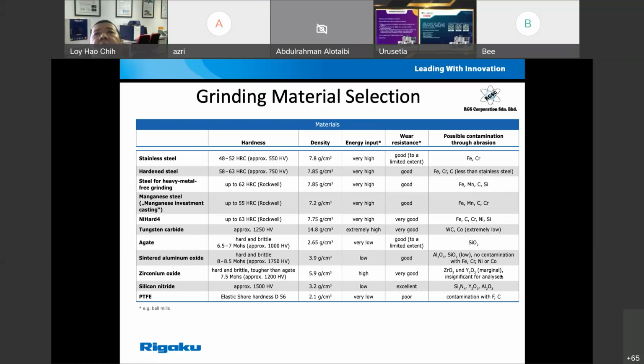For instance, if you are trying to measure iron ore samples and you want to detect the iron, and you are using a stainless steel vessel, then you're going to have a much higher Fe or chromium inside the samples. This kind of error is contributed by your sample preparation. Maybe your samples do not really have such a high Fe or high chromium, but your vessel is contributing to that. So this will give you errors in your measurements.